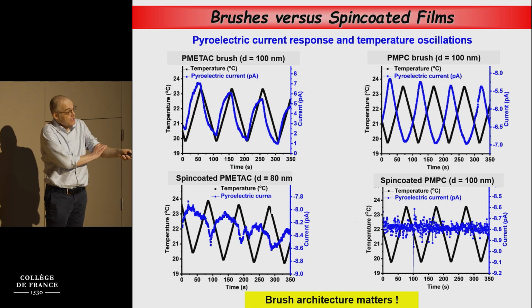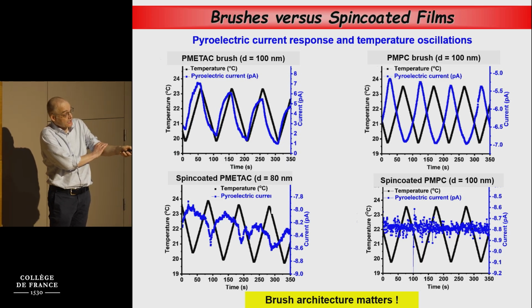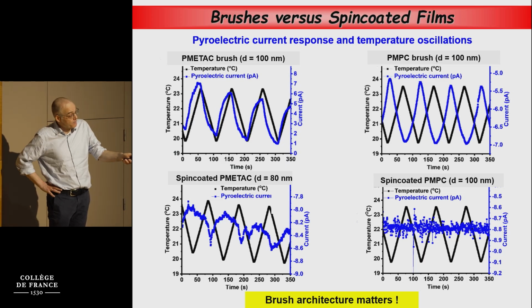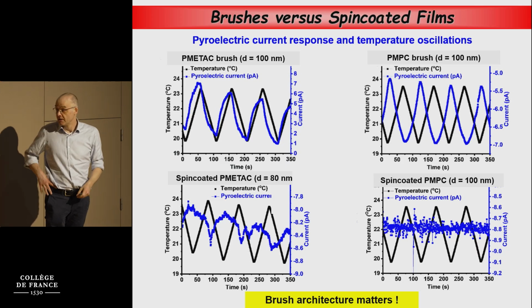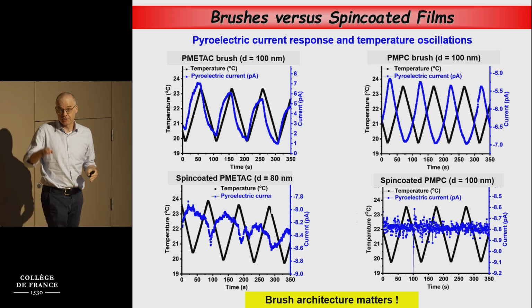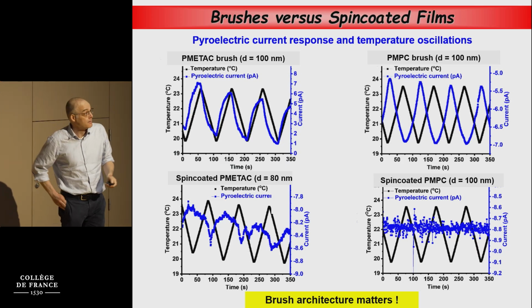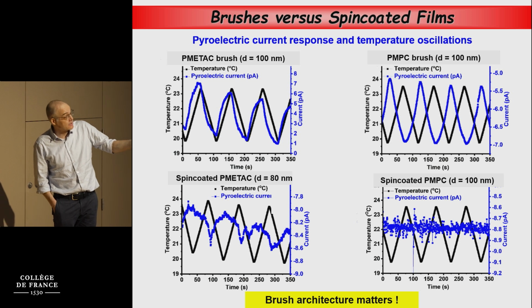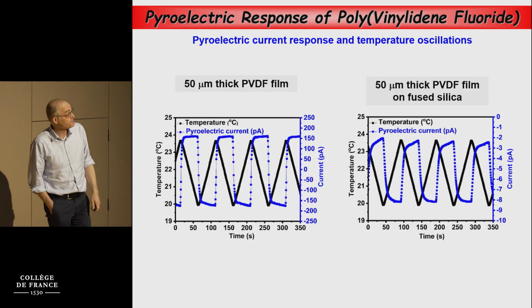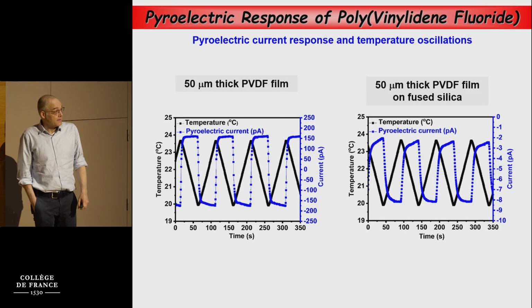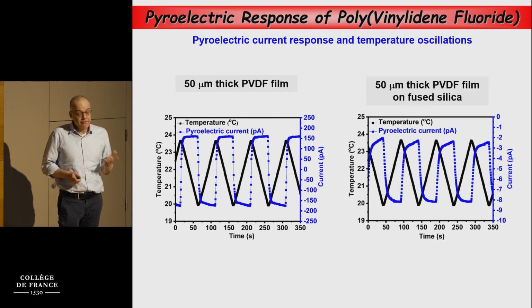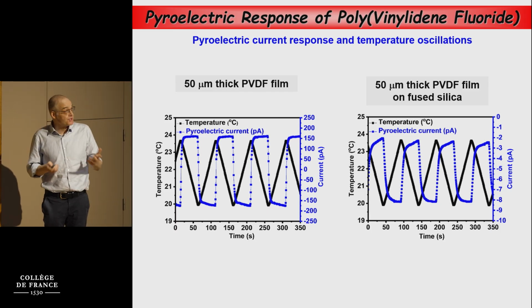So the interesting observation by comparing the data sets on the top and the bottom here is that apparently the brush architecture seems to matter. For the same polymer, the same chemical composition, spin coating versus surface grafting makes the difference between a pyroelectric current and no pyroelectric current. Interestingly enough, the behavior for these films is quite distinct.